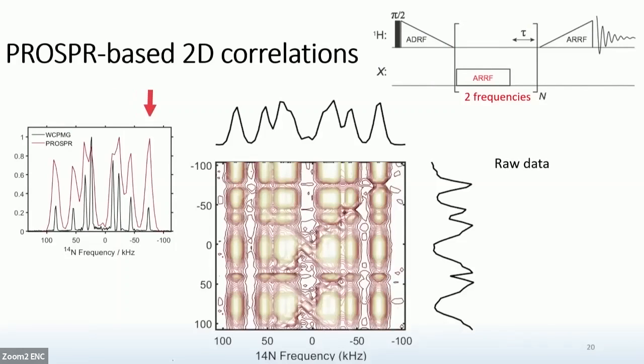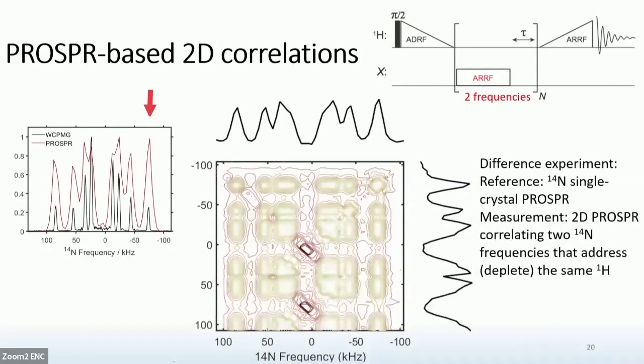So initially, this was the raw data that we got for this single crystal. But then when we plotted the same data as a difference experiment, suddenly we got some correlations out of it. In this difference experiment, the reference is the regular PROSPR experiment, and the measurement is the PROSPR that we did at 2 different frequencies. So what we got here is actually a correlation of each peak here. Actually, it correlates to all the other 8 peaks in the single crystal.